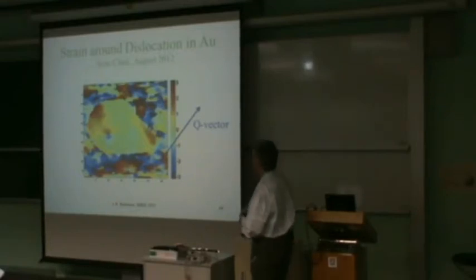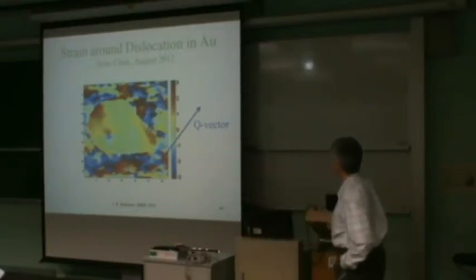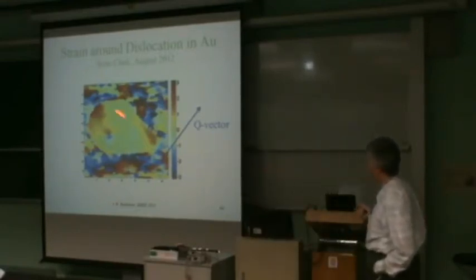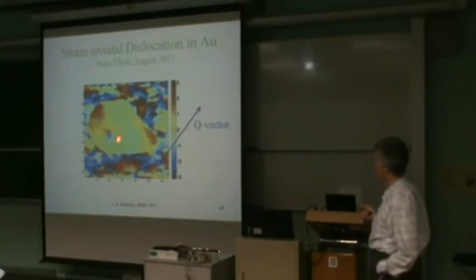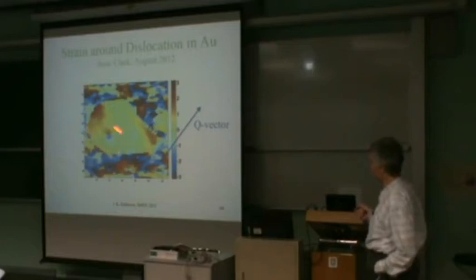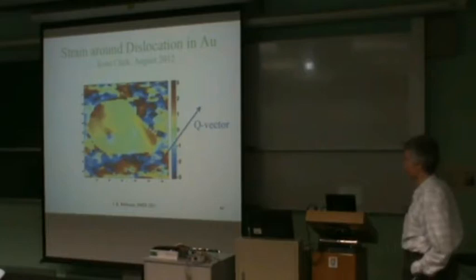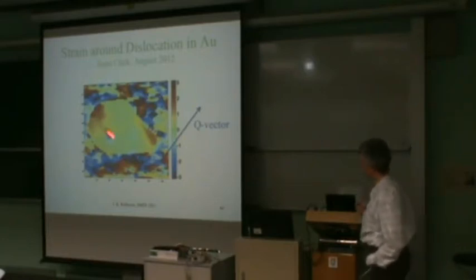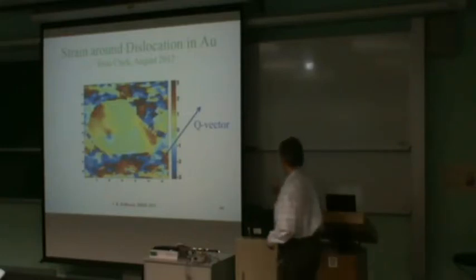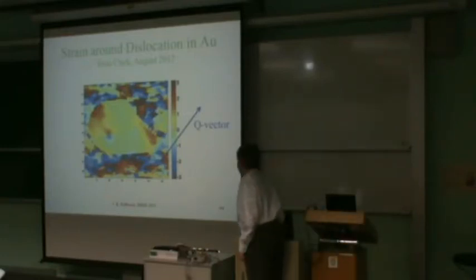Yeah, I do have an example. So this is a gold crystal, but if you section the crystal, you find that there's just one isolated dislocation loop somewhere in the center of this crystal, and you can see very nicely the pattern of this dumbbell-shaped strain field that goes with it. And that's working rather nicely.